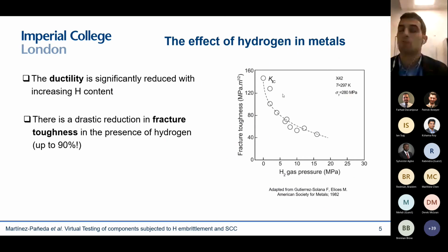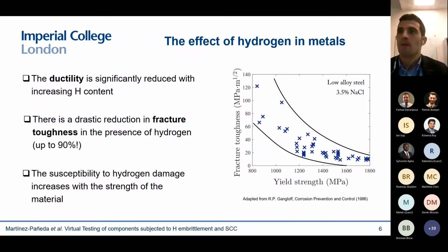And this is a key point to emphasize. The susceptibility to hydrogen damage increases with the strength of the material. You can see here fracture toughness versus material strength. This is for a given environment, so you can think of seawater. And you notice that alloys with very high strength will fail at fracture toughness below 10 megapascals square root meter, so almost like a ceramic.